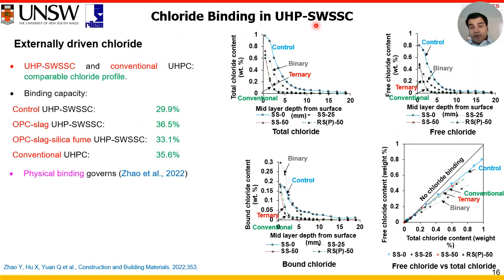So we evaluated the chloride profiles of all types of mixes and found that UHP-SWSSC and conventional UHPC provide very similar and comparable chloride profiles, and the binding capacities of the external chloride from the marine environment exposure fall within a very narrow range of 30 to 36% for all the types of mixes. This means that although we used silica fume, it did not reduce the external chloride binding capacity significantly, which makes us think that the physical binding governs within the microstructure in our mixes.